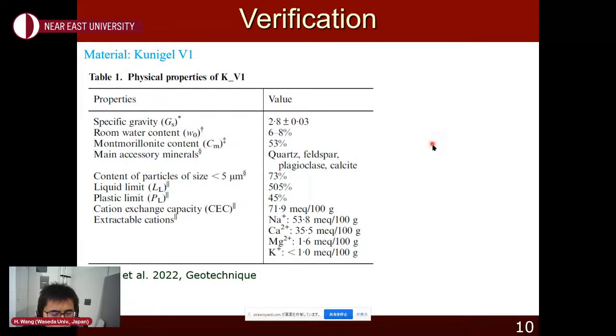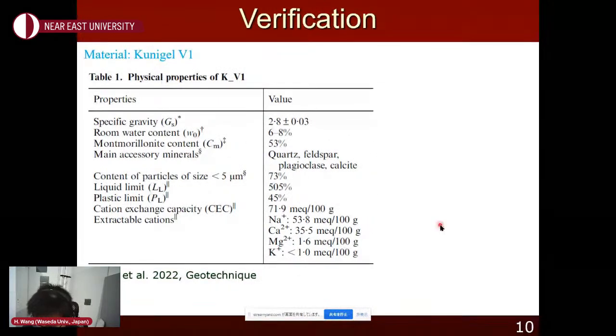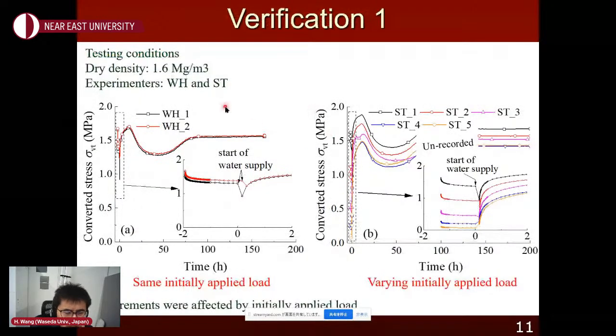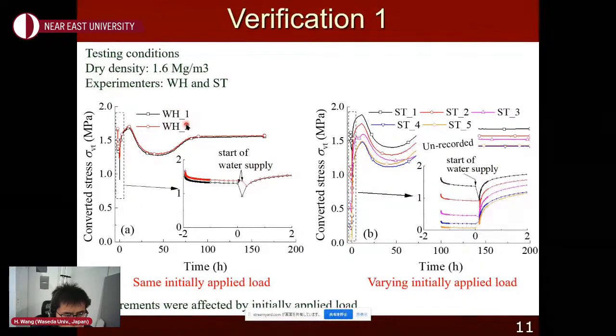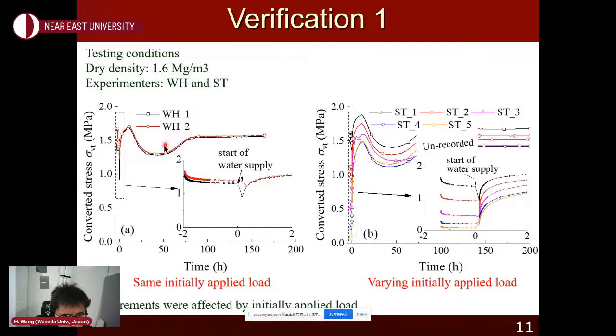So to verify the apparatus, we used a bentonite, so-called Kunigel V1. Here are the basic physical conditions of this soil. We prepared some identical tests, two very similar specimens. We apply the same initial load here, and during the water absorption, we measure the change of the load, or the change of the swelling pressure. This is a very typical swelling pressure curve. It increases first, goes down, and goes up until the equilibrium swelling pressure. This is very typical.